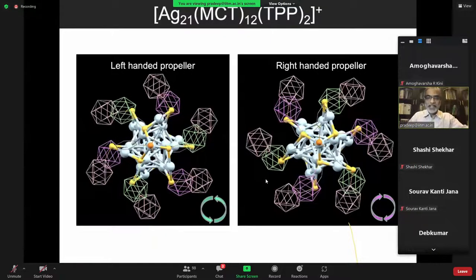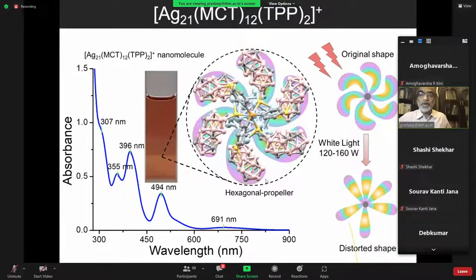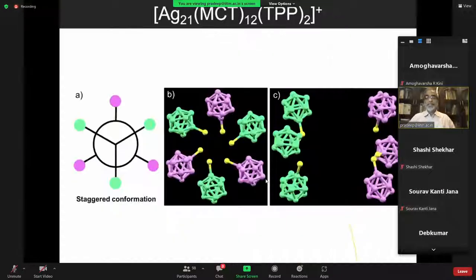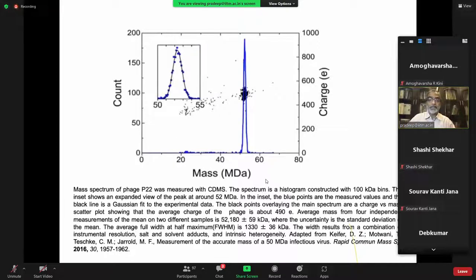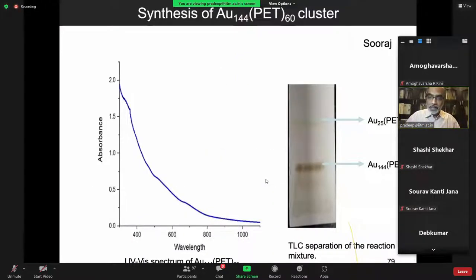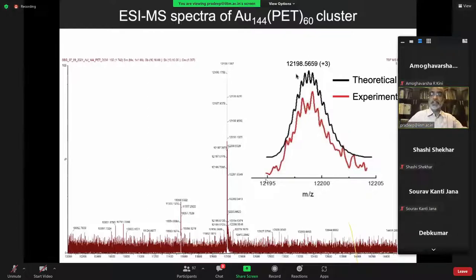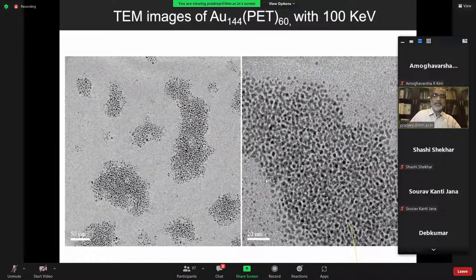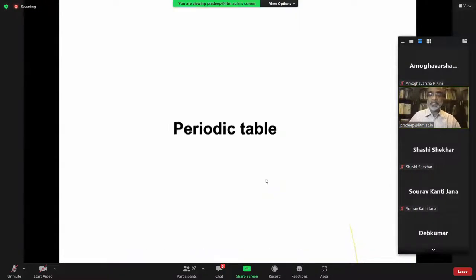It appears as though this is chiral, but it is not, because both the orientations, whether there is a right-handed orientation of these carboranes as well as left-handed orientation, they coexist. Well, you can create larger nanoparticles. Today, with mass spectrometers of, let us say, things like charge detection mass spectrometry, you can go to megadaltons. So nothing prevents you from measuring the mass spectrum of a nanoparticle. Now, we haven't got to nanoparticles yet, but we can measure mass spectra of these. So in this, Suraj is measuring mass spectra of clusters of this kind, extremely high quality mass spectra with precise masses, and their transmission electron microscopy and such other things.